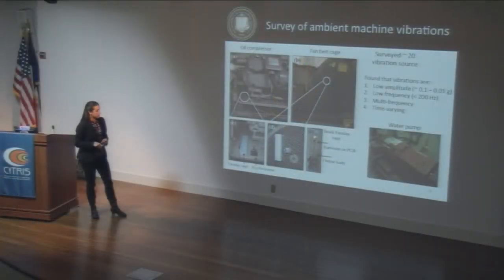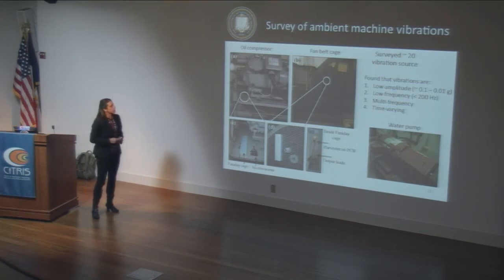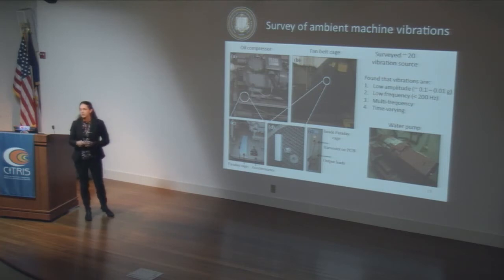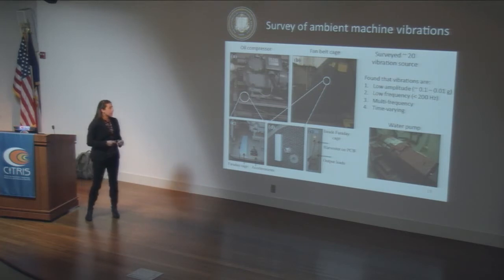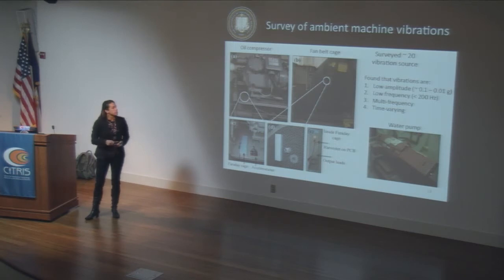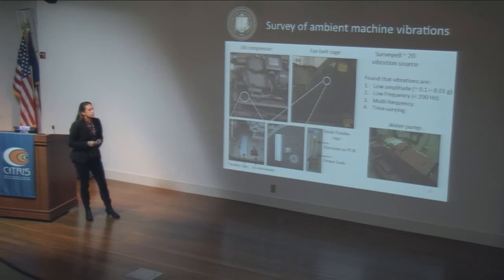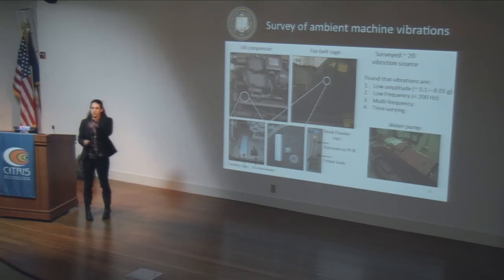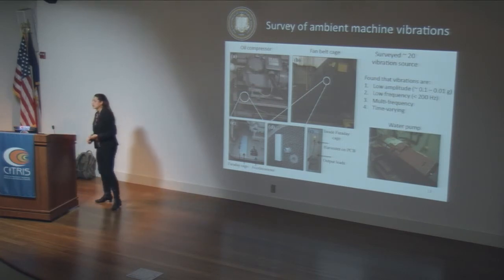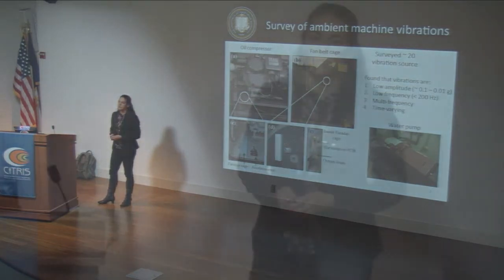So then this shows you how the accelerometer, and inside this Faraday cage box my little MEMS harvester right there, this shows you how the setup was configured. And the main findings from this survey were that the vibrations are low amplitude, typically 0.1 to 0.01 g, low frequency, under 200 hertz, multi-frequency, not just a single sine wave, and also time varying. Those four characteristics of ambient vibrations are really important to keep in mind as we start working on the design phase.